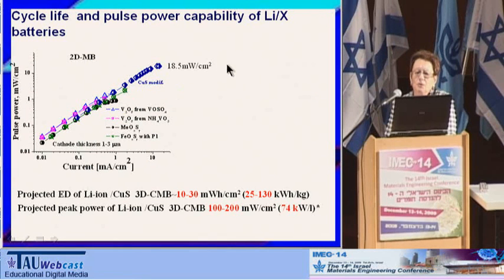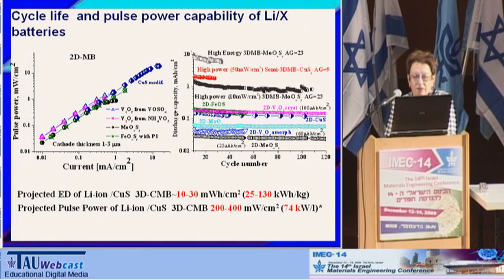The modified copper sulfide cathode, with its pulse peak power of 18.5 milliwatt per square centimeter, even in planar cell configuration, outperforms vanadium pentoxide, molybdenum oxysulfide, and iron oxysulfide cathodes, all of which are prepared by electrodeposition and are under development in our lab.